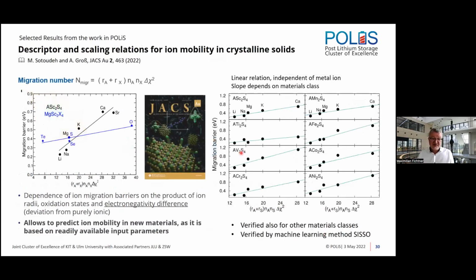Also, this is not very surprising. But if we go to the next slide, we see that you can very easily and nicely describe the mobility in such a system by a thing which Axel called the migration number. And this migration number is just a very simple equation where you have the radii of the anion and the cation, the oxidation numbers of cation and anion, and you have just the difference of the electronegativities squared. And the difference of the electronegativities has intrinsically also some relation between ionic and non-ionic binding situation in it. And you get a surprisingly good correlation, as you can see here.